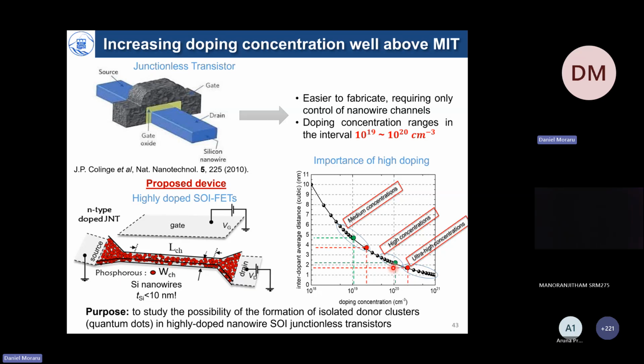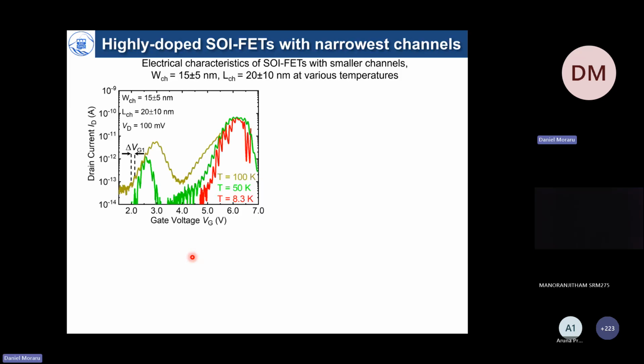We have an opposite problem now. The dopants are so closely packed that there is a metallic conduction between the source and drain. So the purpose of this work was to demonstrate that dimensionality is very important. It is metallic until we build it into nanowires, which breaks down the uniformity of the dopant distribution. I'm showing here only the champion data from our devices, which was obtained for a device with a width of about 15 nanometers and a channel length of about 20 nanometers.